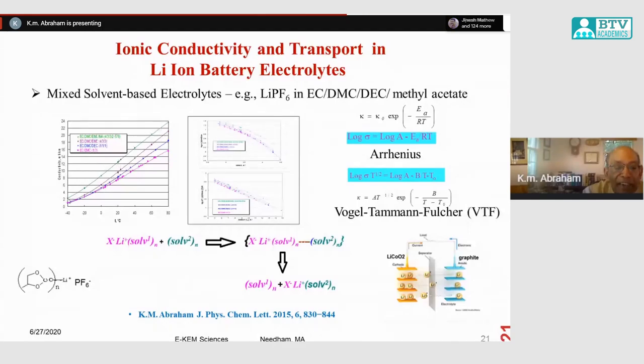You can see that it has good low temperature behavior, all the way down to minus 40 degrees. Ionic conductivity is very important for a battery, because that determines the speed with which the ions move between the electrodes. So the higher the conductivity, the better it is. So this shows how new solvents are created to get both low temperature and high temperature behavior in batteries.